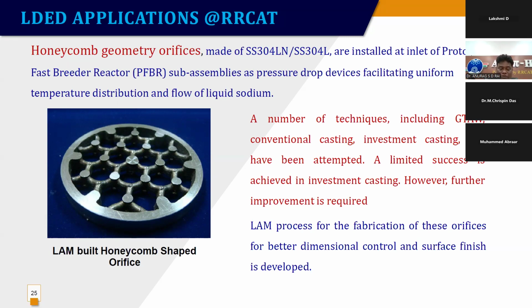So what ideally you need is more sodium to flow in the middle of the core and less on the side, so that these can be done. And then these honeycomb shaped orifices are small pieces. Diameter is around 75 millimeter, and you see the shape looks simple but is very difficult to build.